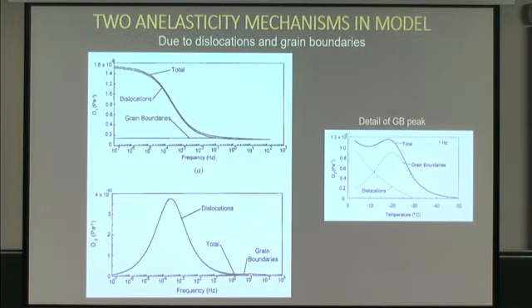This is what they look like. So these are broadened out in frequency space because of alpha, 0.54 and 0.6 for our two mechanisms. The dislocation mechanism, these are loss compliances here, is about an order of magnitude stronger than the grain boundary relaxation. But if you're working on problems either at low temperature or higher frequencies, the grain boundary relaxation could be the most important one you have.